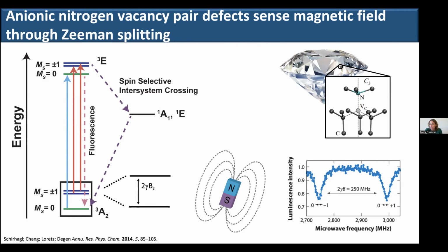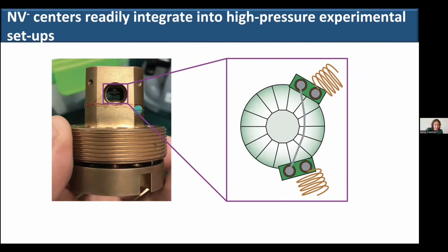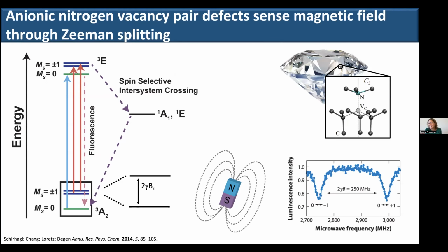So if you know the initial condition, you know where your M sub S levels are, and you know that your M sub S levels split predictably in a magnetic field by the Zeeman effect. If you can read out the splitting, you then know what magnetic field induced that splitting. And so in this way, these defects can be used as optical magnetometers. There is significant work, which I believe I'm referencing on the next slide. I'm not. There is significant work on using these systems as magnetometers across systems.